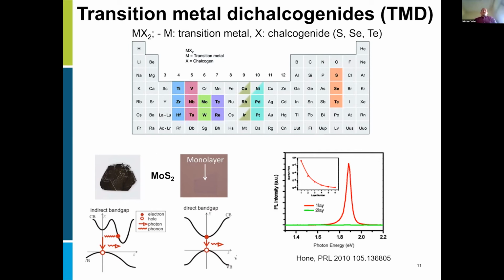So for example, doped silicon is an indirect band gap semiconductor and has to have some sort of thickness in order to absorb enough light. When a material becomes direct band gap, following optical excitation, the recombination of electrons and holes that we create in that material is radiative, so it emits light. And because going from bulk to monolayer one achieves such strong absorption and emission of light, we can see here for molybdenum disulfide the emission from a single layer versus a two layer, so there's a considerable difference.